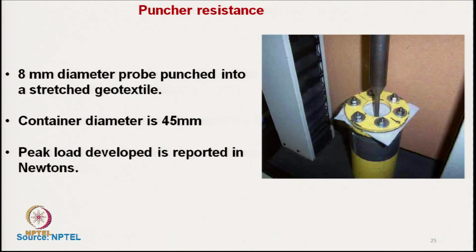Next characteristic is the puncture resistance. Here the puncture resistance is measured by an 8 millimeter diameter probe. This is the 8 millimeter diameter probe, and the container diameter is 45 millimeter.